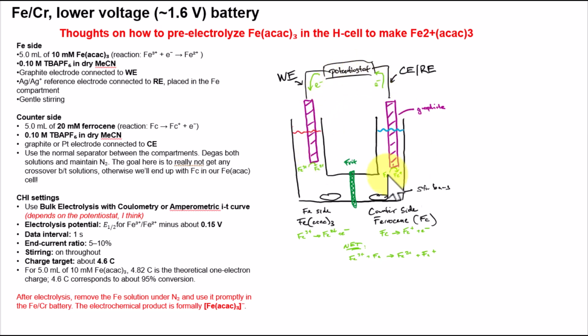And then on the other side over here, we filled this with a ferrocene solution. I think we used 20 millimolar, same electrolyte concentration and composition in both halves of the cell, and then we electrolyzed this. And so this was a big counter electrode. We used a big chunk of platinum on this side, and we just drove the reaction here, and we just used the ferrocene as an electron donor, effectively a sacrificial redox. And we pulled electrons through the circuit over here to make the iron 2 version of this.